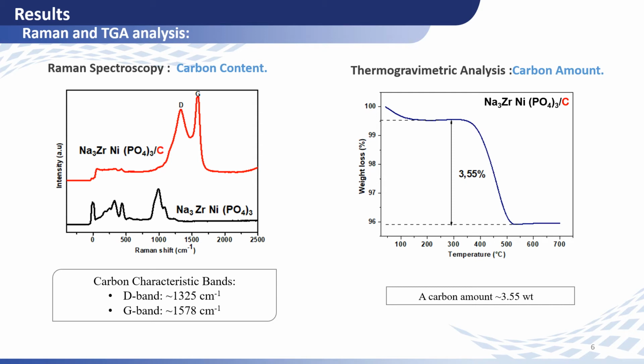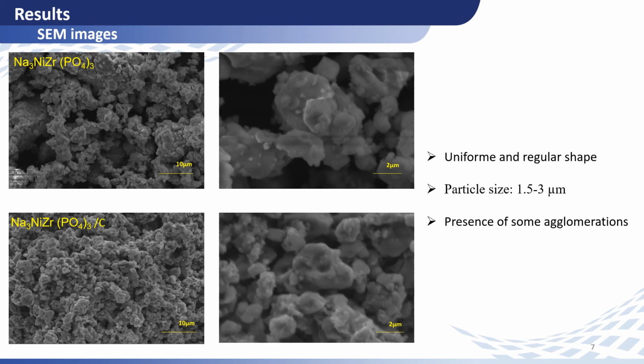We can notice the appearance of two bands, which refer to the G and D characteristic bands of carbon. Thermogravimetric analysis was also employed to determine the amount of carbon. We can notice that we have 3.55% of the total weight of the composite material. The morphological analysis shows uniform and well-shaped particles with an average particle size of 1.5 micrometers. Also, we can notice the presence of some agglomerations in the coated sample.